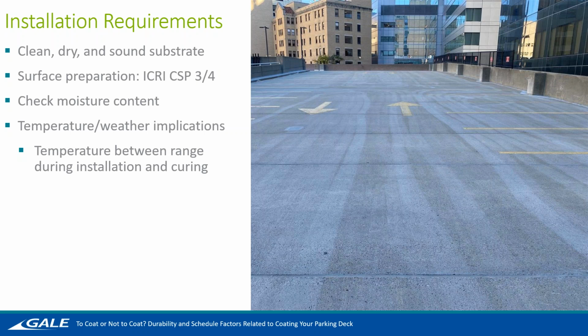So for surface preparation, according to the International Concrete Repair Institute, you're going to want a concrete surface profile of 3 or 4. A concrete surface profile is on a scale of 1 to 10, 1 being no amplitude, pretty smooth, pretty sound, and 10 being very high amplitude, a lot of crevices. You're going to want a 3 or 4 so that your concrete has enough agitation that it will have bite to it and the traffic coating will in fact attach to the concrete, but not so much that, if you have a 10 concrete surface profile, you're going to have a lot of cracks and a lot of ridges that you're going to need to fill, and that's going to do nothing except drive up your costs, because you're going to need more product to get that level base for the additional levels.